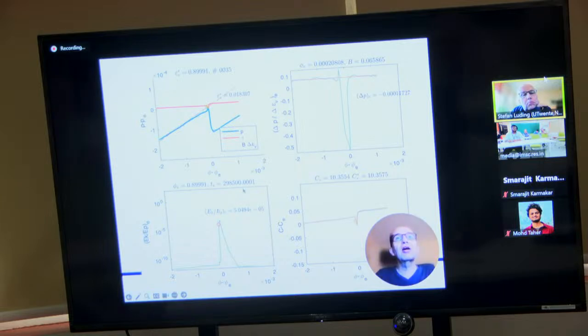At high densities, the situation is slightly different, but some features like the stress drop, the kinetic energy rise, the change in modulus and the change in coordination number can be much bigger because the confining stress is higher, so the events can be much more violent. So this is one example. And you also see the event very isolated, because for high densities, for high confining stress, the events are more isolated than for low confining stress close to jamming. Okay, and all this is taken care of by the probability for isotropic plastic events.